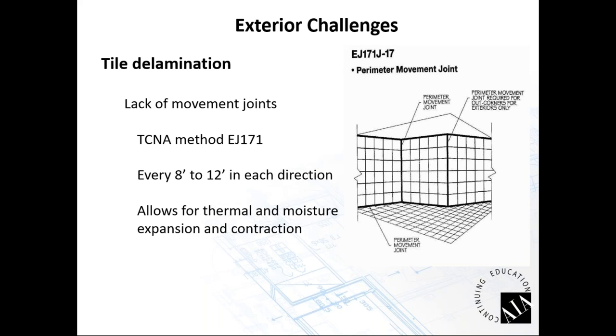Make sure that interior corners and exterior corners are caulked with proper siliconized caulk for these joints. On the corners, one wall might be facing due south where the other wall is facing east, and so there are differences in temperature. Those two walls are moving completely differently from one another. It's important that at the corners we have movement joints so that we don't have a failure of the tile and the loss of bond.